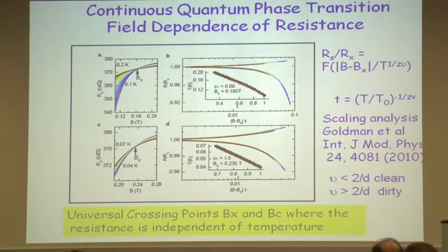And what I have done here is, instead of plotting temperature, we have plotted the sheet resistance as a function of magnetic field. And each of these is actually an isotherm. For a given value of temperature, this is how the sheet resistance is changing as a function of magnetic field. And you will see that at this critical field B sub X, all these curves cross. So this is a uniquely defined magnetic field, again a signature of a quantum phase transition.